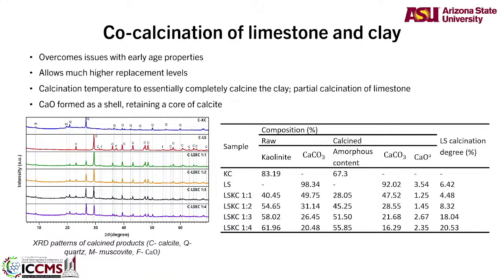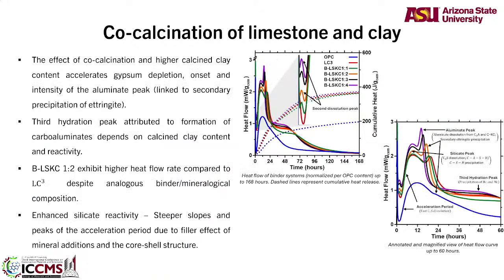Can we co-calcine limestone and clay? And companies are trying to do that. Can you put some limestone and clay together? What happens is you calcine the clay completely. That's about 600 degrees Celsius. Your limestone needs to get to 900. So at 600, limestone is only a little bit calcined. When you get a little bit of calcination around the carbonate grains, you get a little bit of calcium oxide. And then you kickstart the reactions with that calcium oxide, you get very early strength. I'll show you the reactivity curves. You can see here, that's your normal OPC, heat of hydration, reaction early on. You see what's happening.